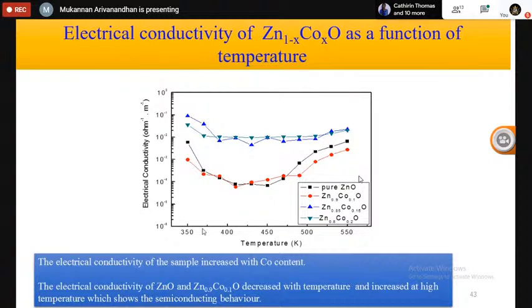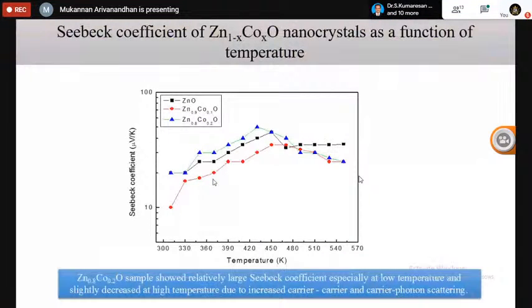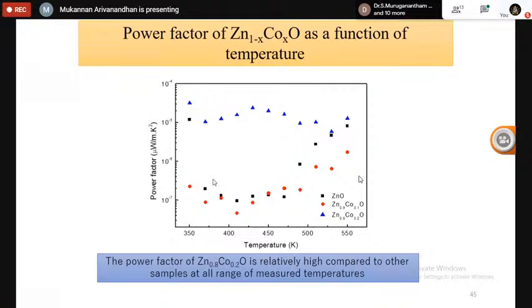The electrical conductivity has been enhanced for the cobalt substituted sample compared to the pure sample, which is mainly due to the heterovalence nature of cobalt in the zinc oxide. Okay, and then the Seebeck coefficient has been measured, which shows an obvious variation with respect to the cobalt content in the system. So from the measured electrical conductivity and Seebeck coefficient, the power factor has been calculated, and the power factor is quite high for the 20% cobalt substituted sample.